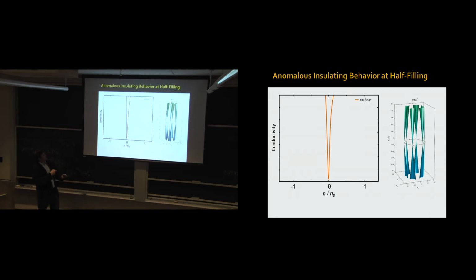I'm normalizing here, I'll show real units in a moment. For now, I'm normalizing the density to what I call NS, the superlattice density, which is how many electrons I can put in this moiré unit cell, which is actually 4: spin up, spin down, valley K, valley K prime. Remember, I told you 4 would appear again.